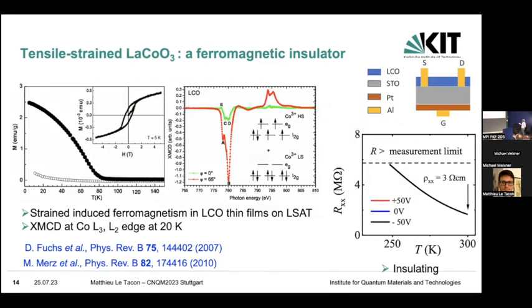So when it's grown on STO, we tried to gate this to really dope it as much as we could, and that's important for after. And we always get a very high resistance of those films, and we never can get those lanthanum cobaltate films conducting.